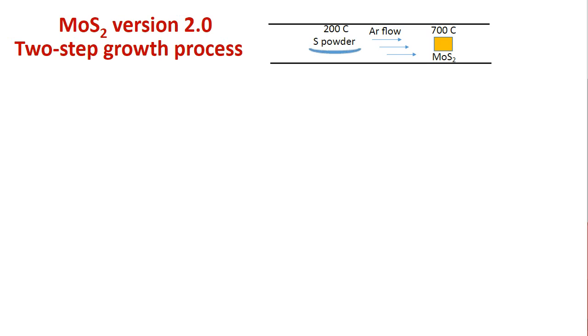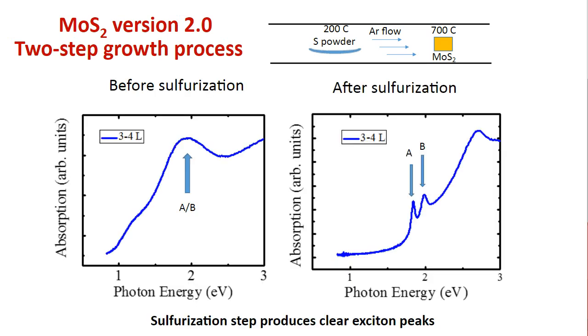Okay. And if it gets replenished, we should see immediate verification through our optical characterization. So that was the hypothesis. And sure enough, we see that. So the data on the left shows the data before sulfurization. Again, this is a 3 to 4 layer MoS2. And the data to the right is the optical absorption data after sulfurization.